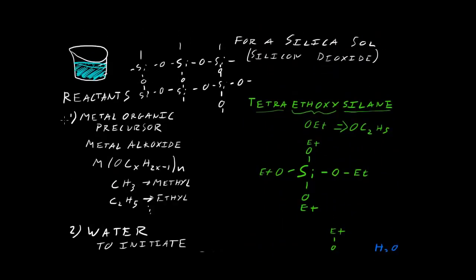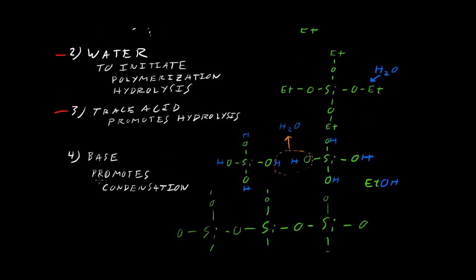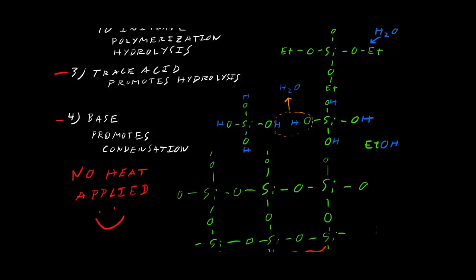But we never added any heat. We added a metal alkoxide, water, trace acid, and a base. At no time did we ever apply any heat. This was all done at room temperature. That is really unique to sol gel processing, and it's one of its greatest strengths.